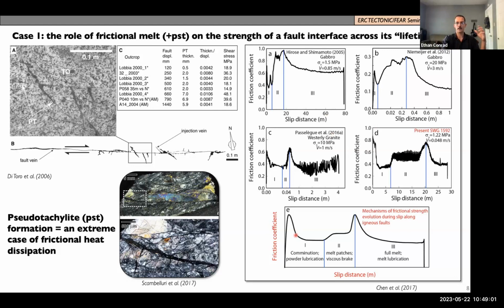And they've categorized this as stage one, where you have comminution and powder lubrication, and the generation of these fine-grained materials increases the surface area of the interface, and it allows melting to actually occur at lower temperatures. And then as you have melt occurring, you start to get into maybe a viscous braking phase, a dynamic strengthening of the interface, and then ultimately towards full melt lubrication.